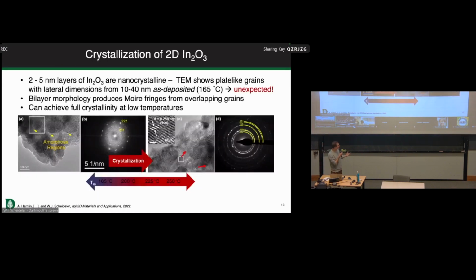Well, it has a few other surprises in store for us. One of the things that we didn't expect initially is that this material can also be highly crystalline as deposited. And this disobeys a lot of the intuition that we had for how these materials are synthesized. So for the most part, there are two factors working against crystallinity. You expect the amorphous phase, because it's ultra thin, that the free energy of forming those grains is really favoring the amorphous structure when we get down to the single nanometer thickness.